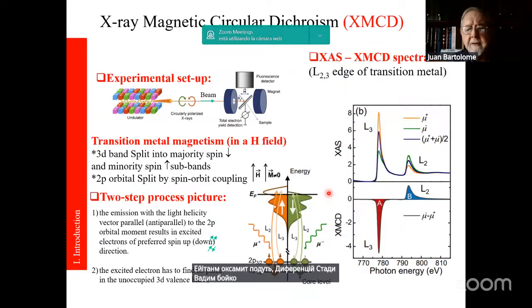But then we come to the X-ray magnetic circular dichroism experiment, which is based on the X-ray absorption technique. The experiment is as follows. From the insertion device, we have a beam of photons circularly polarized to the right or to the left, and a magnetic field which is parallel to the beam, impinging on a sample which is on a turning table. We can orient this turning table in any direction. So the photons emitted will then be detected by the adequate detectors around.